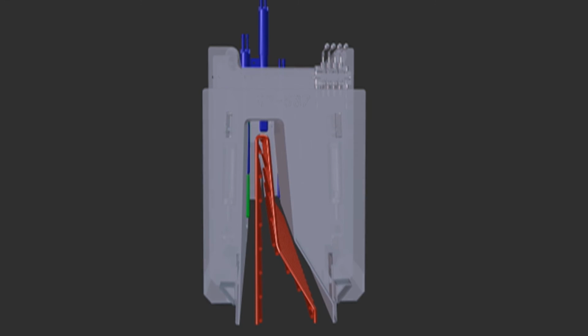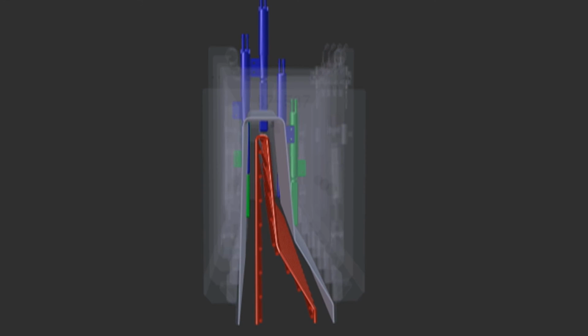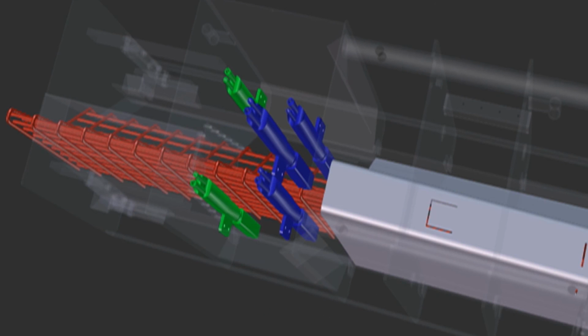Our last example is a barrier or parapet poured over a steel cage. The positioning will be similar to a standard barrier. Two down low, mounted on the front of the hopper, and the rest attached to the back of the hopper. Great care must be taken to make sure no vibrators touch the mold shell or the rebar cage. This would cause unwanted vibrations and could collapse the wall.